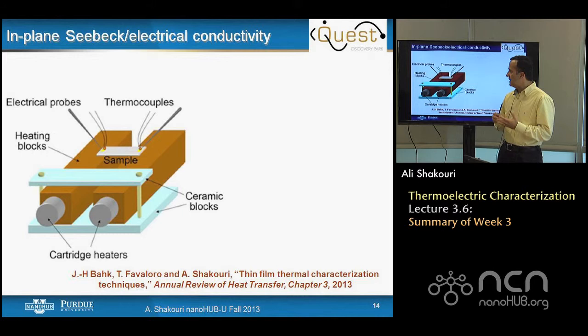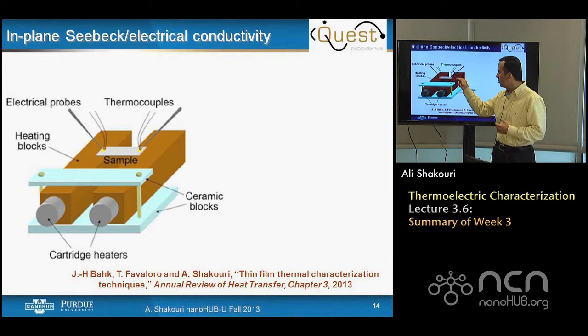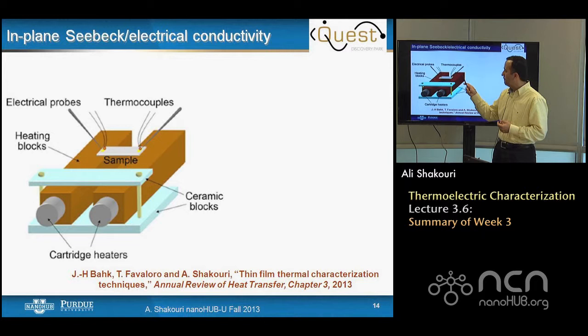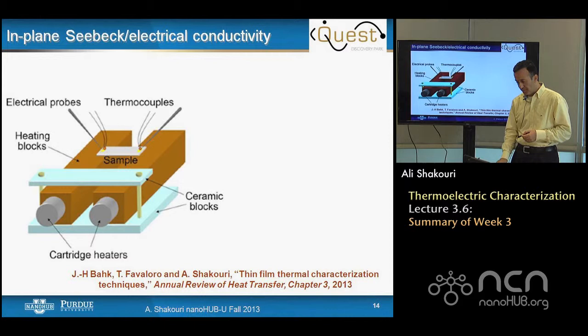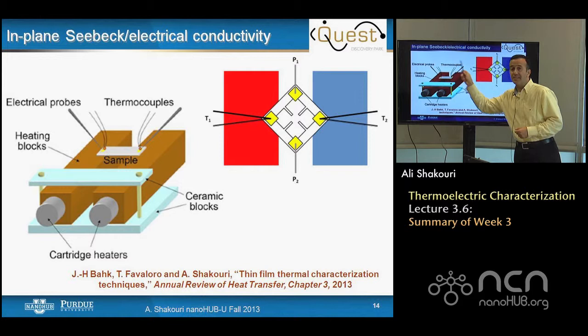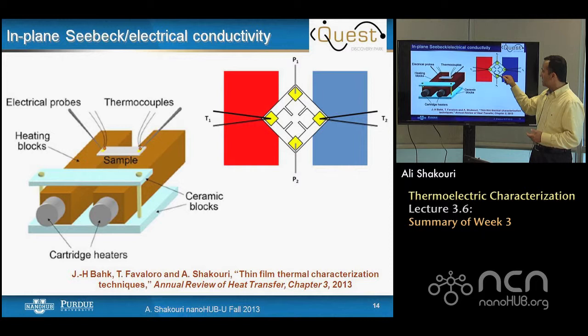For in-plane Seebeck measurement, you place a sample with one side hot and the other cold and measure a voltage. The key challenge is ensuring you measure temperature at the same point as the voltage, so often one of the legs is used as the voltage probe. Good thermal contact — via thermal paste or pressure — is also essential. You can also use a van der Pauw or similar technique to measure in-plane electrical conductivity and Seebeck coefficient simultaneously with four probes in specific patterns, avoiding sample-to-sample variations for more accurate data.